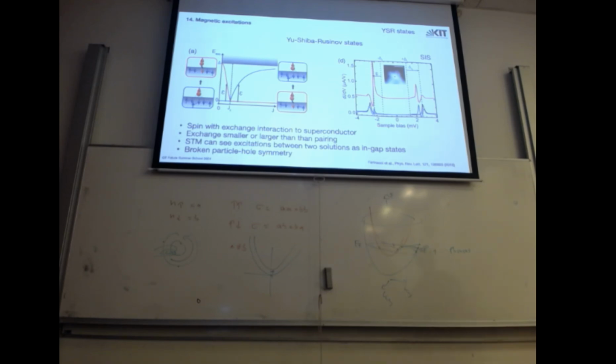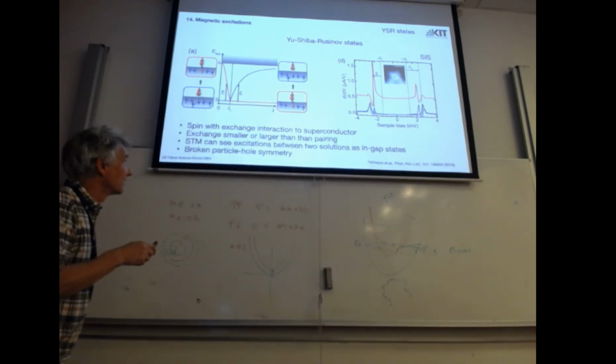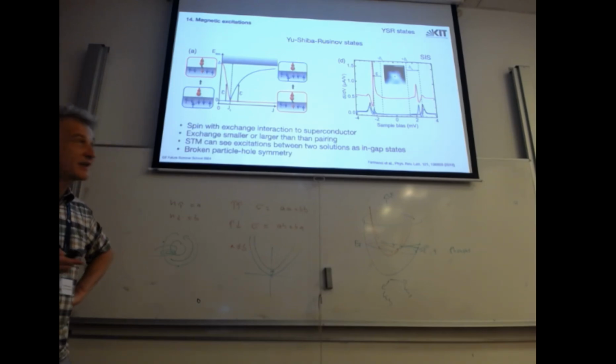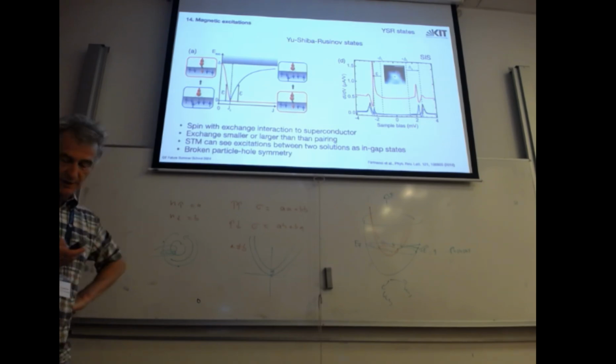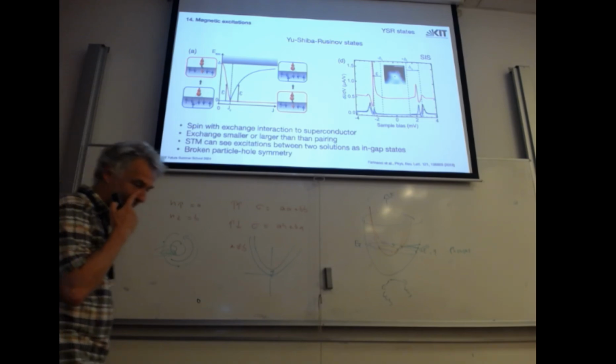This is an experiment by Wulfhekel, where you have such an impurity somewhere, and it's superconducting tunneling, SIS tunneling. So two gaps added on top of each other is this black curve, and inside these two gaps there is this sharp state, which has the energy epsilon, and this is exactly this excitation energy. Similar to the Kondo effect, you can understand this as screening and localizing the spin, and it shows up as single particle states in the spectrum inside the superconductor gap. Okay, so we will need that later.